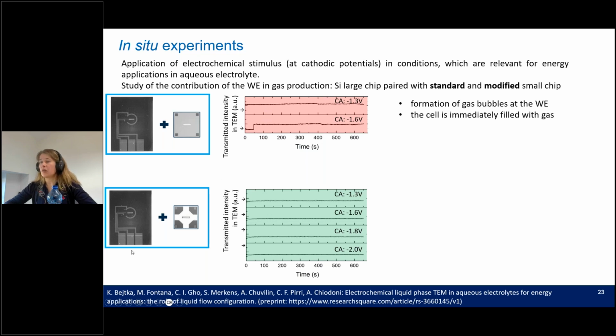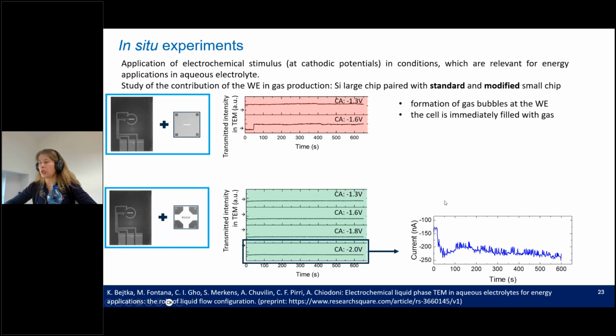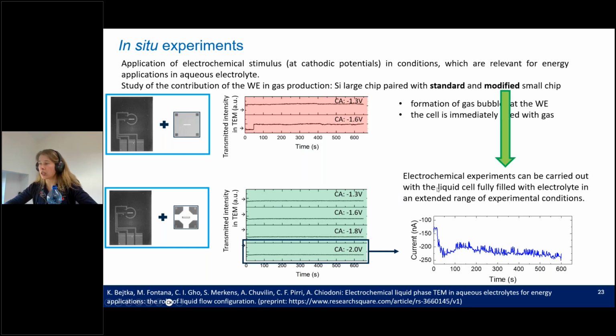In the modified cell, we observe that the chronoamperometry can be run. The potential of -2 volts versus platinum, we were running it smoothly for 10 minutes, and we know that actually it can be run for even longer times. And these experiments can be carried out with the liquid cell fully filled with the electrolyte for the extended time, as I mentioned.